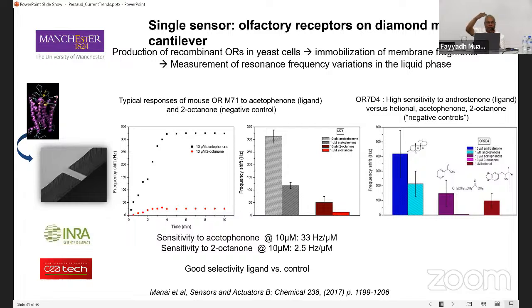So it responds to mass. So if something hits the surface, it will bend, and we can measure that bending. And we can put diamond onto it, we can put proteins onto it, and we can measure the response of that cantilever to vapors. So what we see here is the response of this cantilever, put in an olfactory sensor, to the vapor of acetophenone.